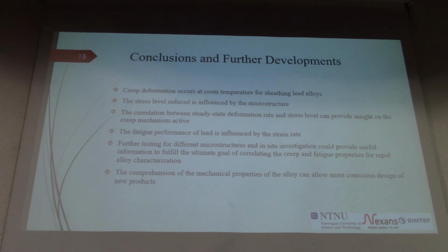So yeah, to conclude, we observed that for this material we have creep deformation at room temperature, that the stress level is influenced by microstructure, and we can have an insight on the deformation active by looking at the correlation between the stress applied and the strain rate that we obtain. And these effects have an influence on the fatigue life at different strain rates. So in the future we would need further investigations for different grain size, and in situ testing would be also useful to try and understand better which are the mechanisms active on the material in order to have in the future a more conscious design.